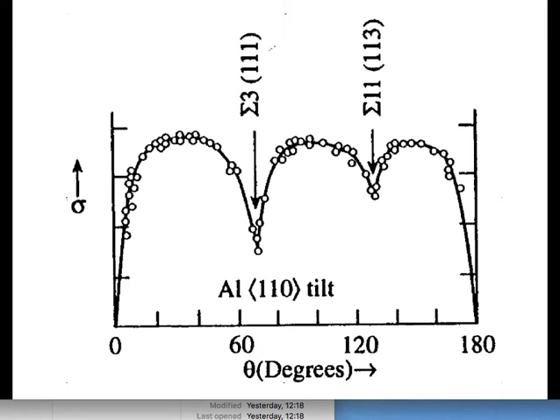So a sigma 3 CSL means one third of lattice points coincident. So would you expect a sigma 3 or a sigma 5 boundary to have a lower energy? Three, because a larger fraction of lattice points are coincident, right? And you can see that the sigma 11 boundary has a higher interfacial energy than sigma 3.